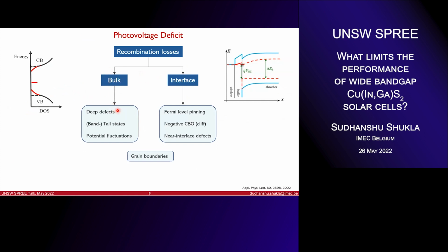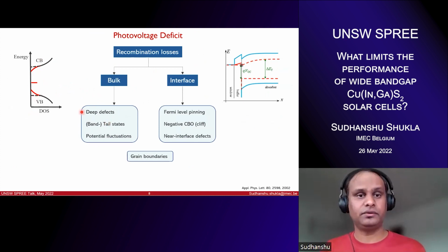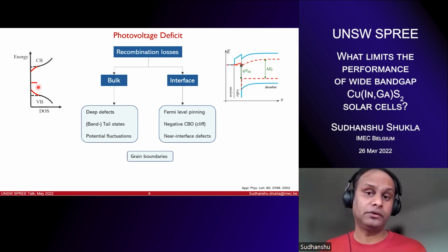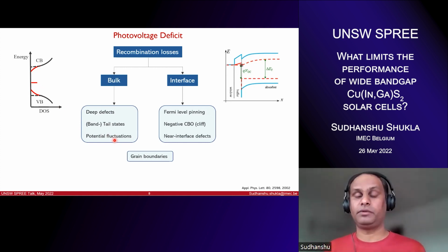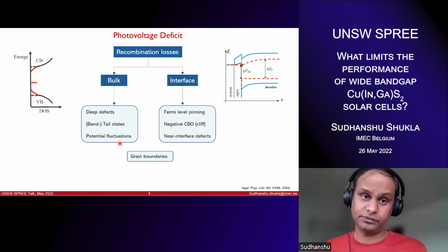in the bulk, and there could be a bunch of reasons. One, we all know, is the deep defect within the band gap, which is like a killer defect, limits the lifetime and is responsible for the carrier recombination. We can have these band tails where the recombination can occur, and that also can account for hundreds of meVs of losses. And also you can have potential fluctuation if you have a very high degree of compensation, for example. One such example is copper-poor CIGS selenides, where you do have these potential fluctuations, also in kesterites, for example.